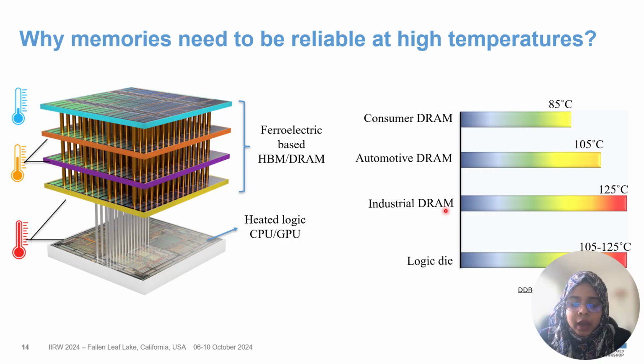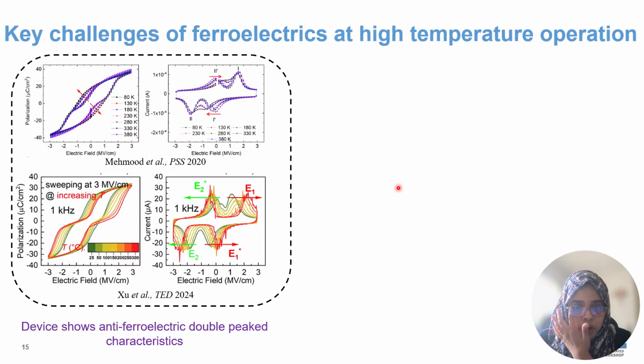But if we look into the performance of ferroelectric memories at higher temperature, those are also not very good in the initial case. For example, in this plot, the green curve is coming from room temperature measurement, and the red one is coming from high temperature measurement. As soon as we go to higher temperature, we get more and more pinched loops, and more and more double peak behavior in our switching current.